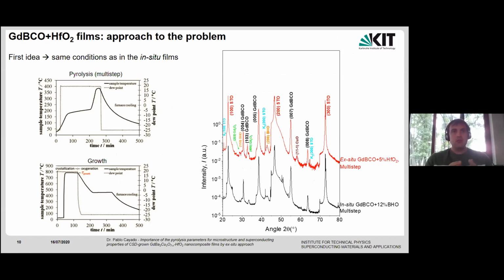So when we start to work with this type of colloidal solutions, we observe certain problems, certain troubles that we try to solve, and I will explain how we solved the problems that appeared. Initially, our first idea was to say, okay, we have nice in situ films, gadolinium plus hafnium oxide plus barium hafniate films. They are working nice. So why don't we use the same conditions as we use for this in situ approach with this colloidal solution? So then we decided to start with this pyrolysis step, which is the conventional one.